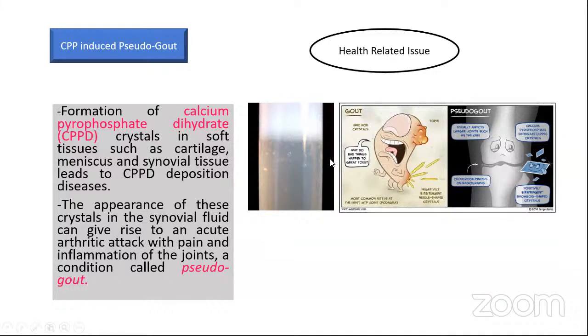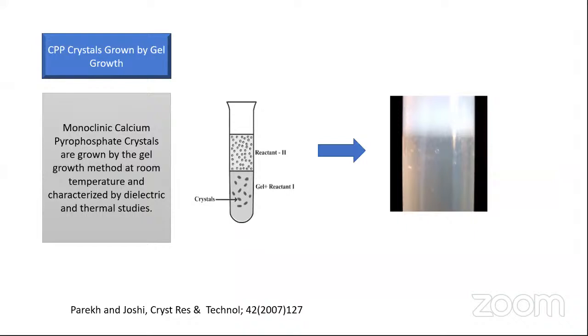And these are the crystals of calcium pyrophosphate grown in a gel medium. I'll explain the gel medium in my morning talk, where we grew hydroxyapatite crystals. Here we have grown calcium pyrophosphate crystals. Monoclinic calcium pyrophosphate crystals are grown by the gel method at room temperature and characterized by dielectric and thermal studies. The gel is a sodium metasilicate gel, set by adding a suitable acid. Once the gel is set, a suitable solution is added on top of the set gel without disturbing it, and that solution diffuses into the porous medium of the gel. A reaction takes place in the porous medium between the two reactants, and they produce a crystal. So these crystals are grown in a gel medium.